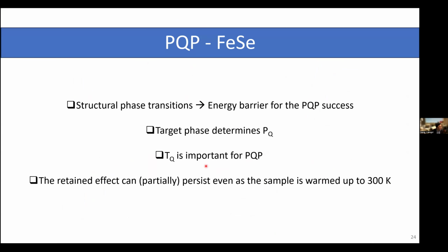Okay, so from this set of results, there are a few takeaway messages. First, the assumption we have that structural phase transitions provide the energy barrier for PQP success seems to be reasonable. And the quenching pressure is normally determined by the maximum TC we want to reach. But here we want to emphasize that the quenching temperature is very important. It's not only the pressure, and not only how fast you release, but releasing at the correct temperature plays a very important role. Also, this experiment shows us the retained effect can persist, or partially persist, even as the samples warm up to room temperature. So that's really positive news.